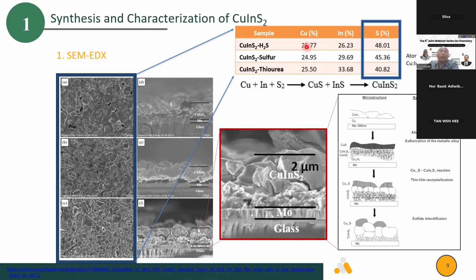Actually, the best way to get the copper indium sulfide should be copper 25, indium 25, and S almost 50 here. But for this case, this is around 48 and 45, 40. So this is almost 1:1:2 here. We never find the precise value for copper indium sulfide, as my previous work also resulted like this. We can see here the microstructure and then the relevant mechanism of the copper indium sulfide here.